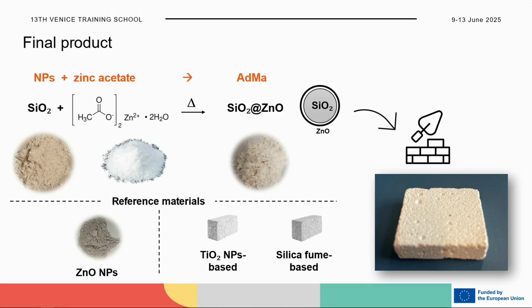According to this case study, we selected 2 different types of reference materials or benchmark. It depends on the definition that you would like to have. But anyway, during the synthesis, we characterize the material and we use zinc oxide nanoparticles as a reference material because the outer shell of our advanced material is made up of zinc oxide nanoparticles. And then during the use phase of the material, so in the final application phase, I would say, we compare some of the characteristics of this material with 2 different mortars, titanium dioxide nanoparticles based or silica fume based, that are already available on the market.